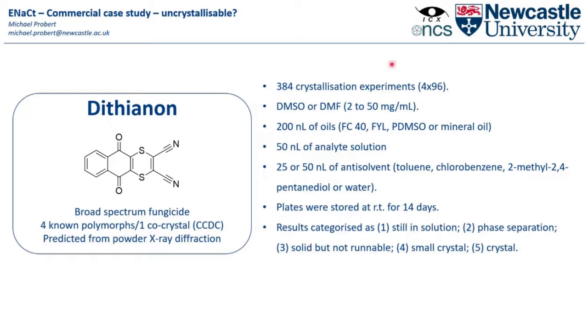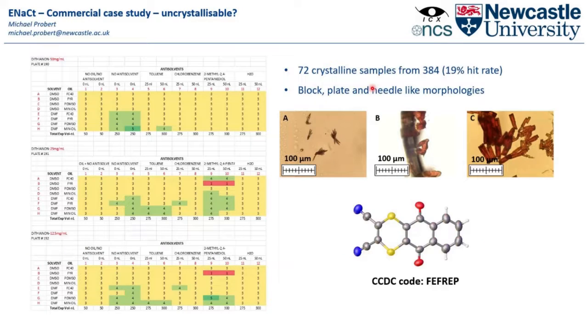And there's some experimental conditions set up on the side, but in the interest of time, we won't go through those. We'll just skip through to the headline act, really. And that is that, yes, we can. So we get these crystallizations resulting. Good success rate, in that within a 2-week period we had access to different crystals that we could run and actually gain full structure resolution from this. So from a commercial point of view, compounds that are difficult to work with, have proved difficult to crystallize before, this technology seems to work very well for.